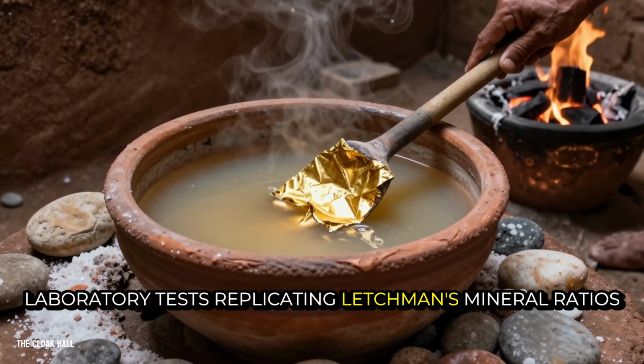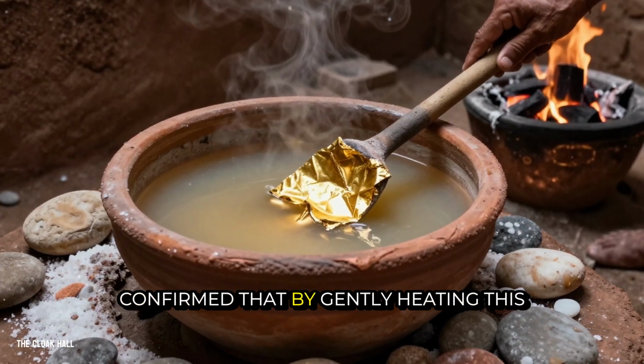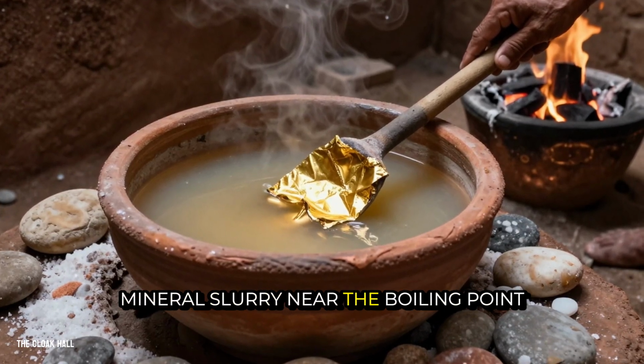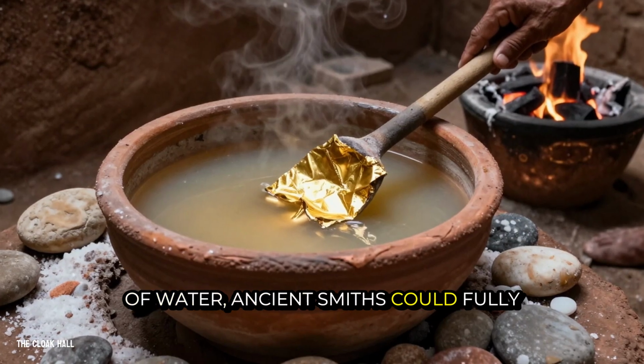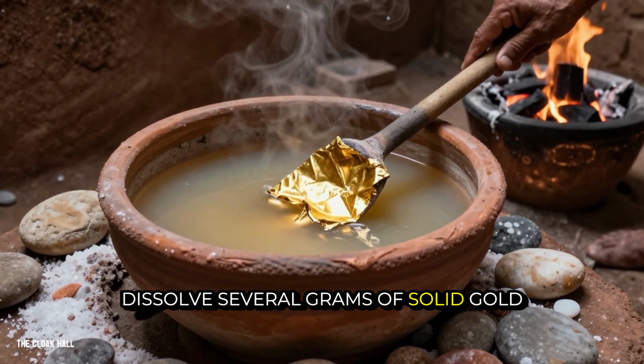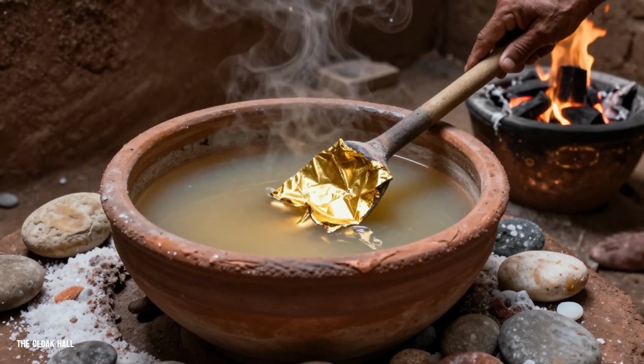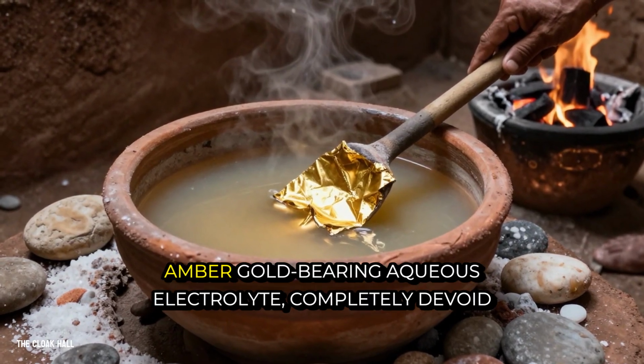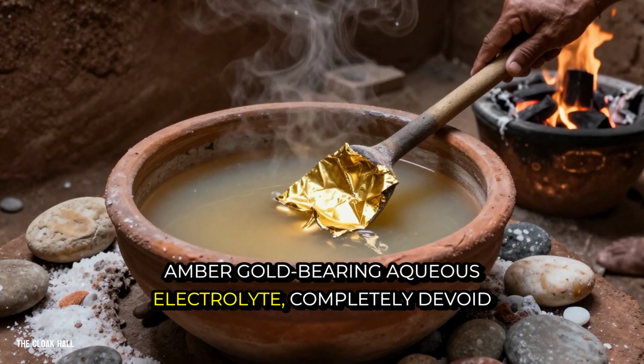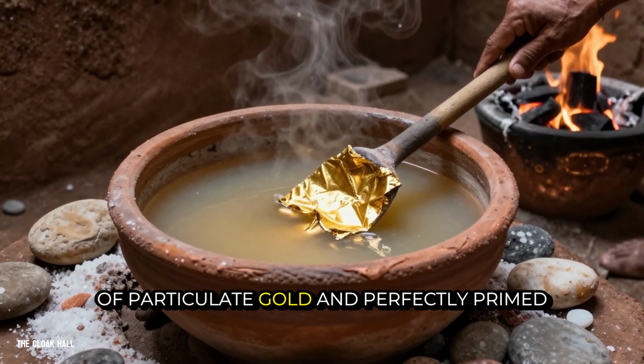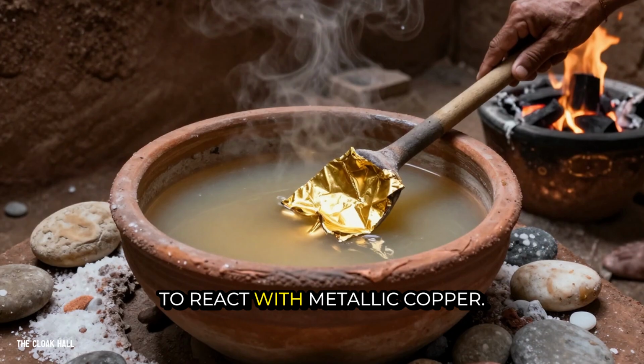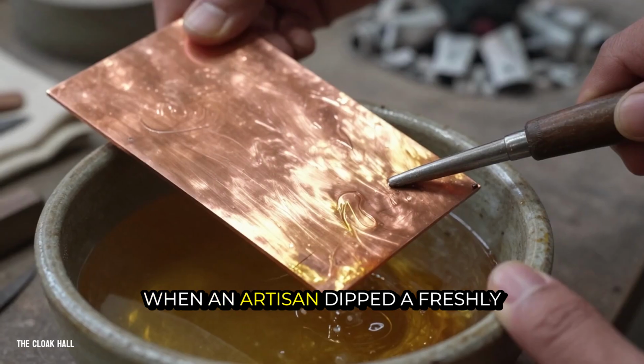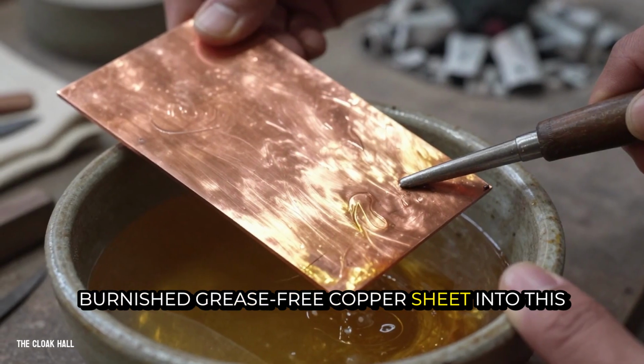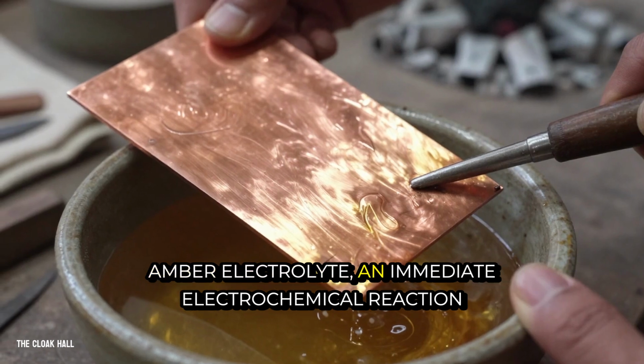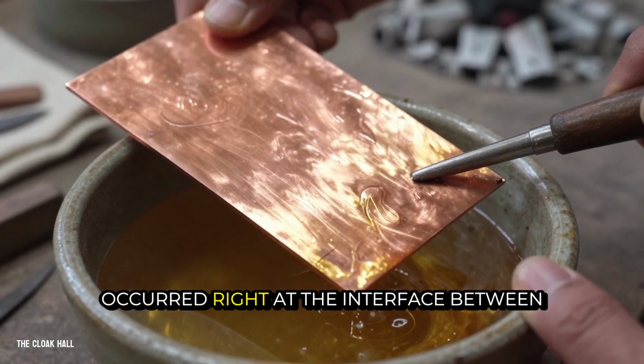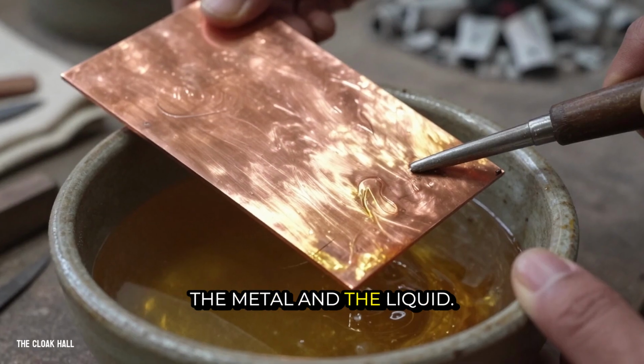Laboratory tests replicating Letchman's mineral ratios confirmed that by gently heating this mineral slurry near the boiling point of water, ancient smiths could fully dissolve several grams of solid gold foil within a few days. The result was a clear, slightly amber, gold-bearing aqueous electrolyte, completely devoid of particulate gold and perfectly primed to react with metallic copper. When an artisan dipped a freshly burnished, grease-free copper sheet into this amber electrolyte, an immediate electrochemical reaction occurred right at the interface between the metal and the liquid.